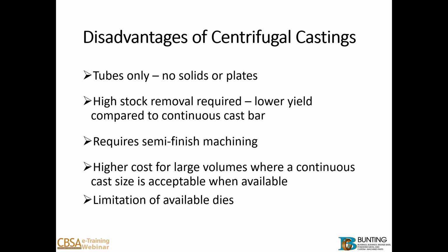Primarily speaking, we want to semi-finish it to make sure we've got good solid metal, and then also you don't want to pay for more metal than you need. So our industry typically sells this as a semi-finished blank. Higher costs for larger volumes where continuous cast is acceptable when available. So it can be more expensive than continuous cast if you're making something simple with an ID/OD. Limitation of dies. Remember, the die is a central part of making a centrifugal. So if I don't have the right die or your supplier doesn't have the right die, it can be more expensive than it should be. So there are limitations there.